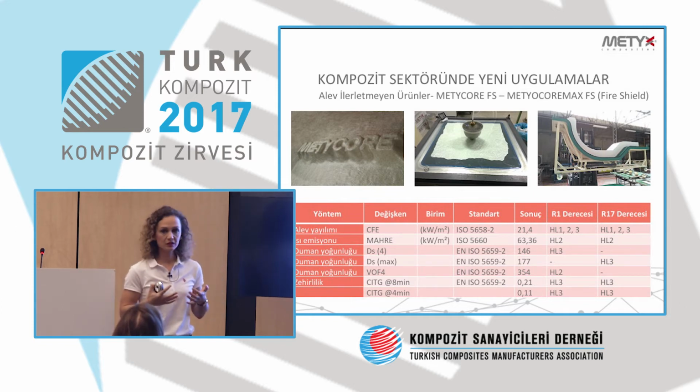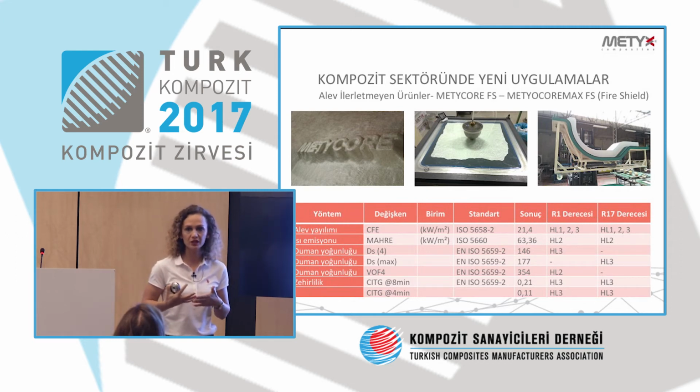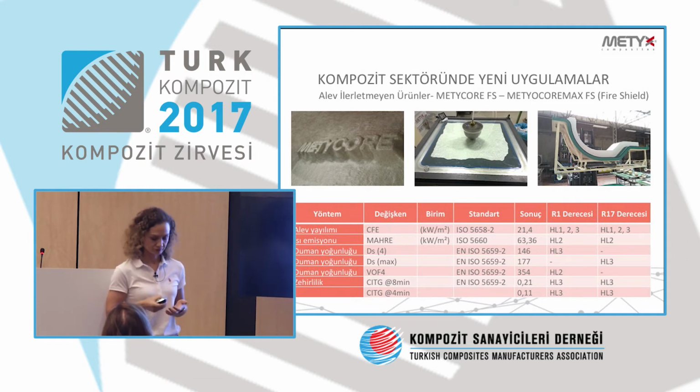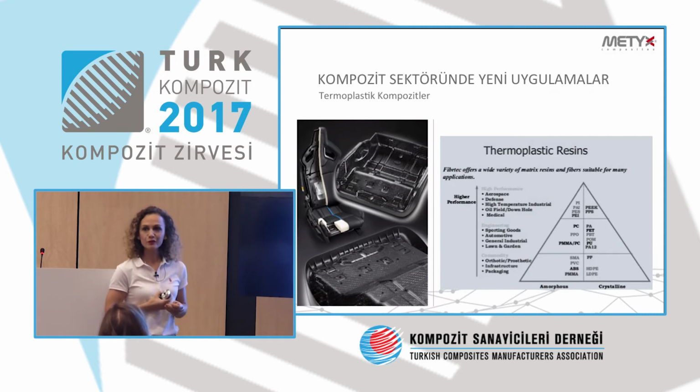So RTM is also used. If you cannot, you should also think about the porosity of the fiber. And here, what can I suggest to you? If you are preparing a thin piece, these thin pieces can catch fire more easily. Thick ones do not, and that's the reason why they can pass the tests easily. So in this case, you need to increase the amount of glass. Since it is a synthetic fiber, you need to think about increasing the quadriaxial, multi-axial glasses. And as a result of this, you can receive better results. This is all I can say about this matter.